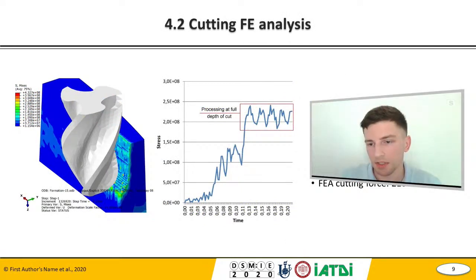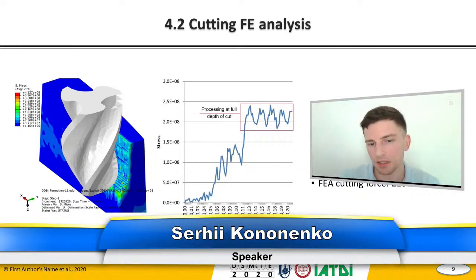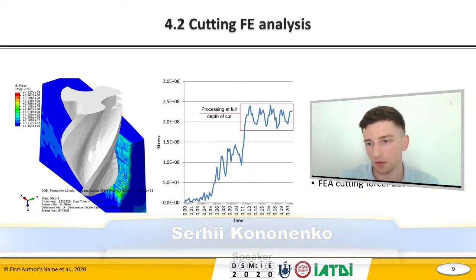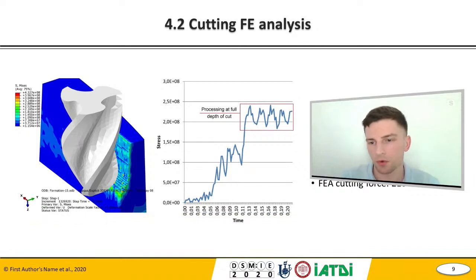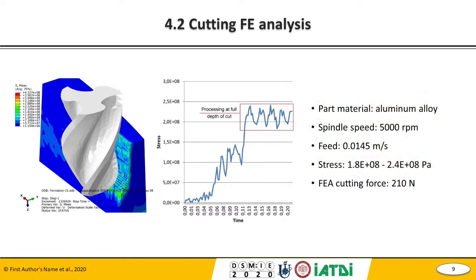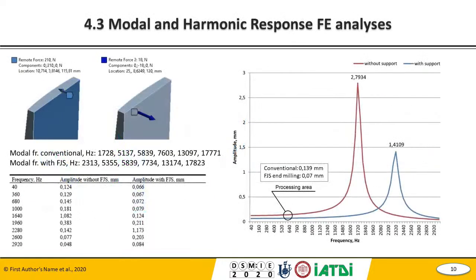So, cutting finite element analysis. We performed it for a quarter of the part to reduce computational costs. We used aluminum alloy as the material. The width of the cut was near 3 millimeters and the depth 1.5 millimeters. From the finite element analysis we got a cutting force equal to 210 newtons. Next slide, please.